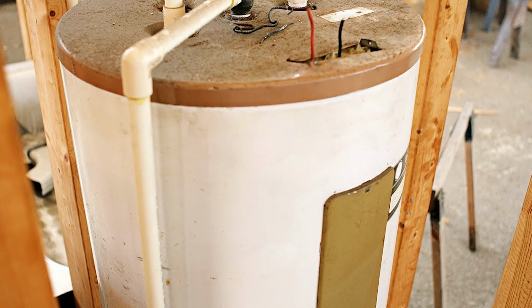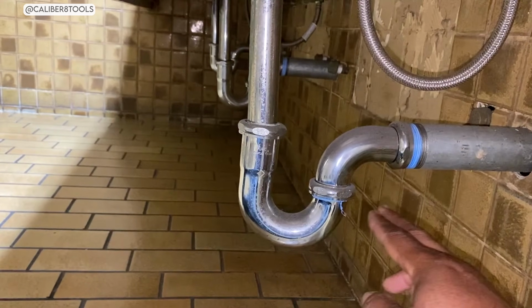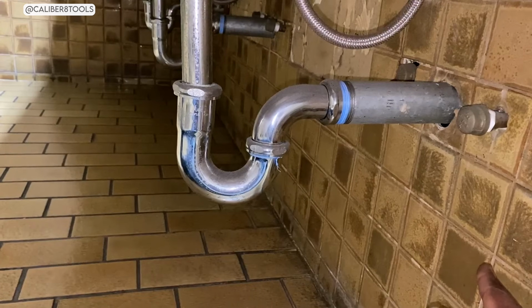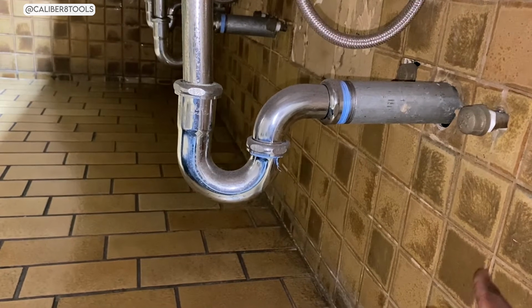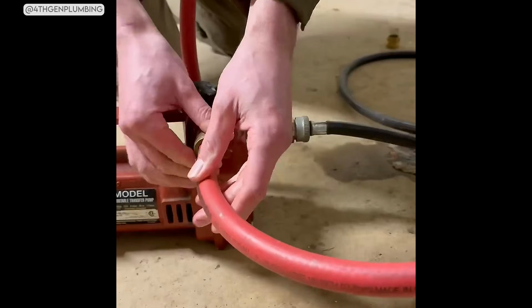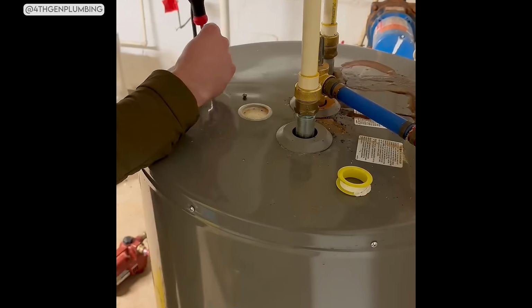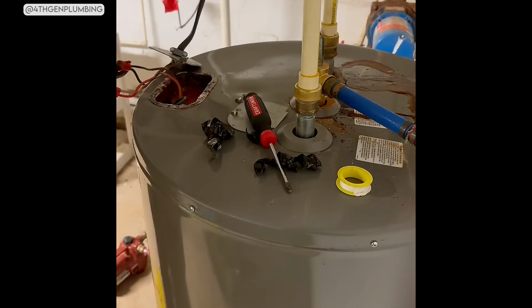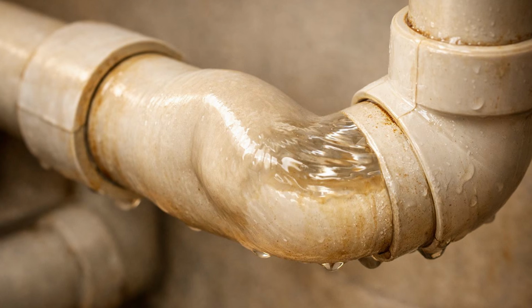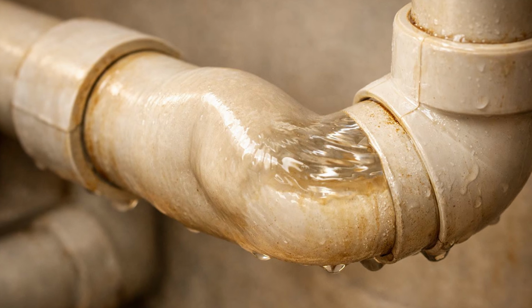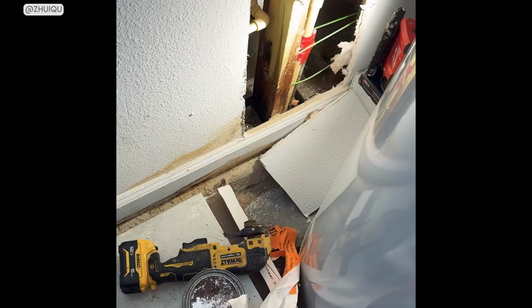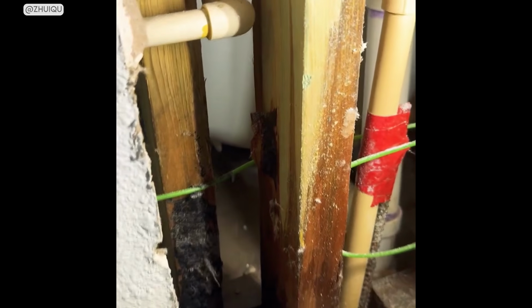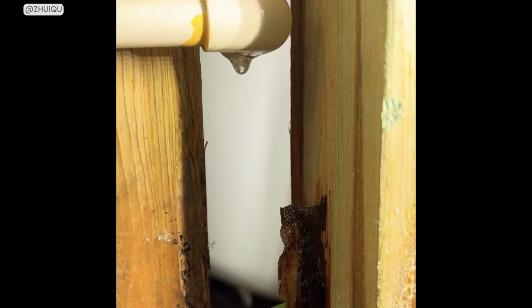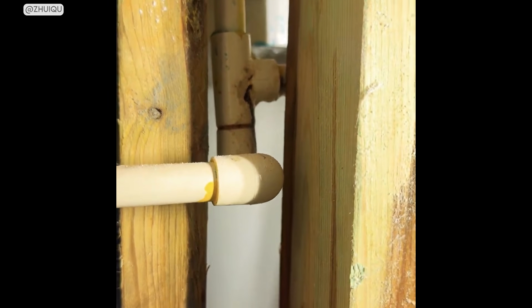It is not appropriate for hot water supply lines, for connections near water heaters, for steam applications, or anywhere the pipe might face sustained heat from an external source like a furnace flue, a heating element, or direct exposure to an appliance. The most common place this mistake happens is hot water supply connections under kitchen sinks or in utility rooms near water heaters. For a while, everything seems fine because the joint holds at startup. Then the pipe slowly deforms with each hot water cycle. Joints that were perfectly aligned begin to pull at subtle angles and eventually leak.